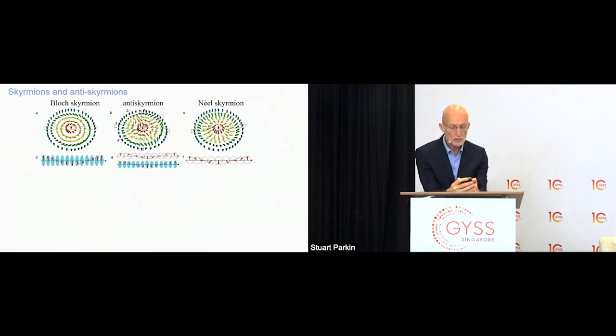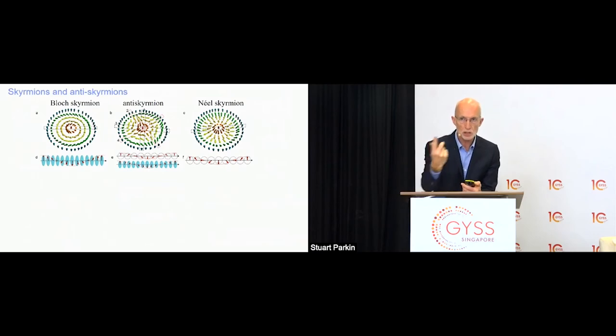And the reason is the same Dzyaloshinskii-Moriya exchange interaction that favors perpendicularly magnetized moments. This means that you can lower the energy of the system by forming, as shown in this cartoon, circular objects in which there is a domain wall in which the moments are aligned perpendicular to one another. So the Bloch skyrmion has a structure in which if you go from the outside where the moments are out of the plane to the inside of the object where the moments are in the opposite direction, the moments will rotate from the up to the down direction in a plane which is tangential to the surface of this object. It's called a Bloch skyrmion. The important point is that rotation of the magnetization will either be clockwise or anti-clockwise, depending upon the material system.